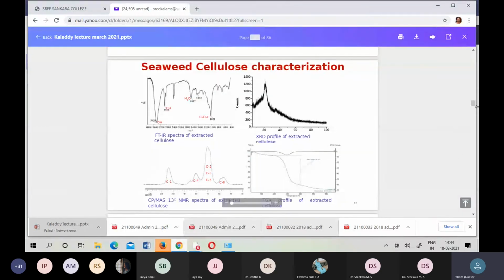These ash contents are quite stable beyond 500, 600. So the remaining mass, close to 30% mass, we are matching with the mass related to the ash content. And there is the peak close to 21 that belongs to XRD and other functional groups. Of course, it's expected, 3,400 to 3,600 belongs to the hydroxyl because the cellulose has a lot of OH, whereas the specific functional group of C-O-C is lying somewhere close to 1021.